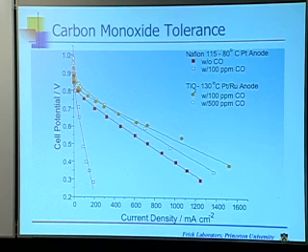No, that's a very important question. First of all, it's kind of interesting. The CO poisoning at these kinds of low levels, in particular CO, does not happen instantaneously. It takes several hours to just see the effect. You know, so if you do a really quick look, you'll say, no problem. We have run these cells only for about 10 hours. These curves were all taken after 10 hours, so that it's a fair comparison.